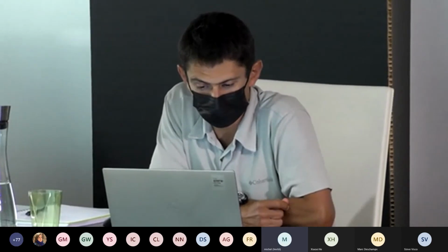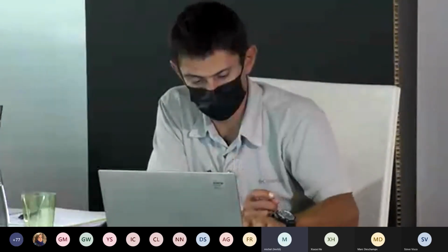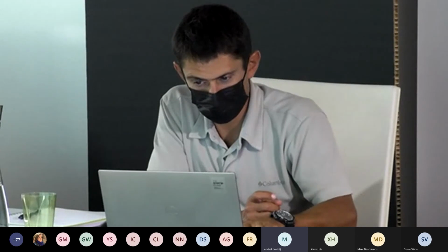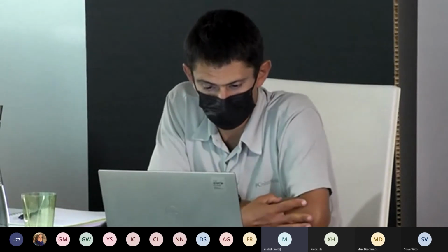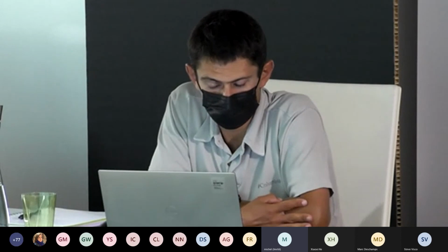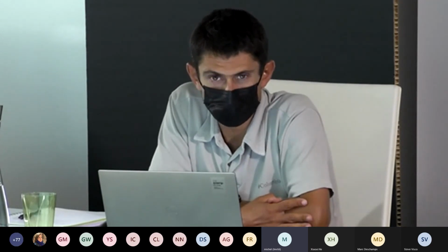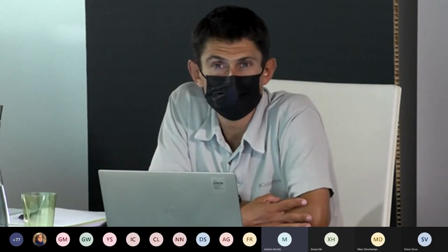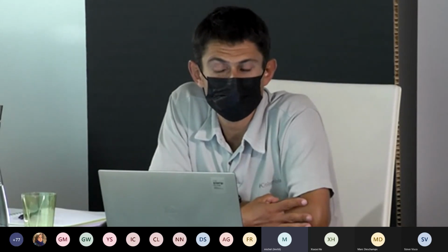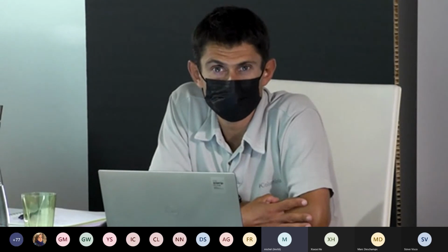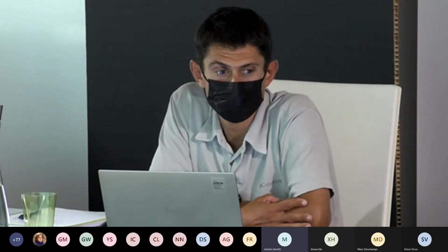I mean, it's going to be a tight race between sulfides like the one I showed, which are multi-grain ceramics, which are pressed, possibly bound with a polymer to make a composite, or polymer electrolytes for the ease of processing. So I think clearly between composites and pure polymers. And of course, the thin film glasses that Steve Visco showed have extraordinary promise, but not for a totally solid-state system as is disclosed.